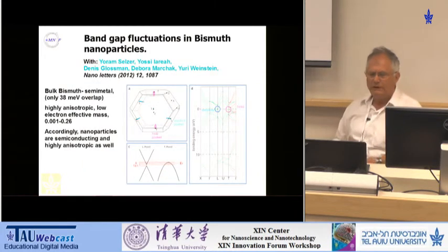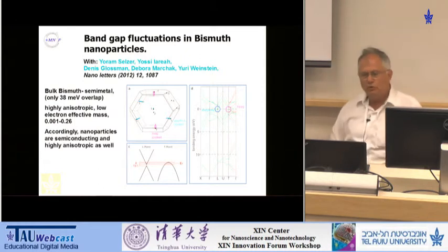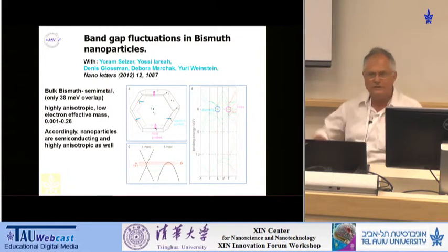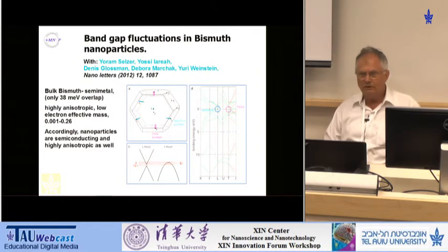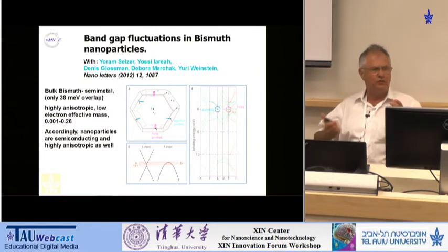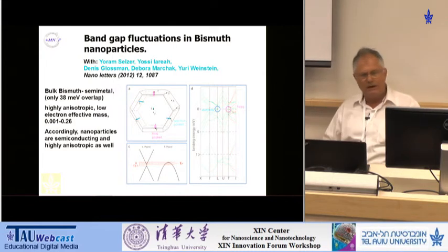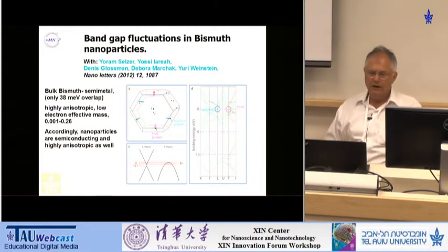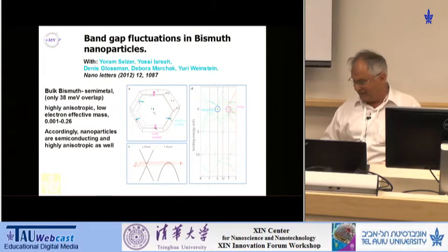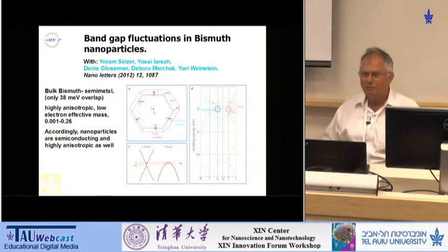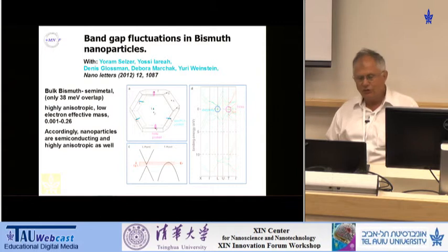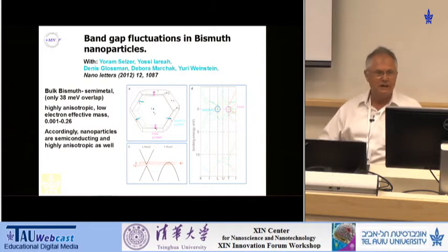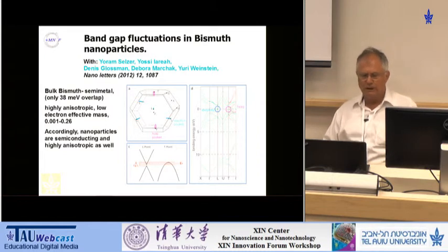And now to the subject matter of the current presentation. It has to do with the fact that nanoparticles are expected, if they are to serve some technology, to be stable. And they are believed to be stable. You form a uniform distribution or single size of nanoparticles, then you hope and you believe that the properties are well defined. And what we have seen, well, at first we didn't like the idea at all, is that the nanoparticles that we are checking are extremely unstable, and for some reasons that I will explain later, we can see that very obviously in bismuth nanoparticles.